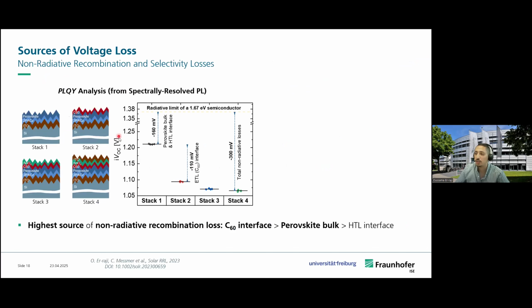In terms of non-radiative recombination, we can do photoluminescence measurements from which we can extract the quasi-Fermi level splitting, alternatively labeled the implied VOC. So here we had different stacks, a stack until perovskite, a stack until C60, and then different functional layers, to understand the impact of different interfaces on the non-radiative recombination losses. So here in stack number 1, we found an IVOC of 1.22 volt.